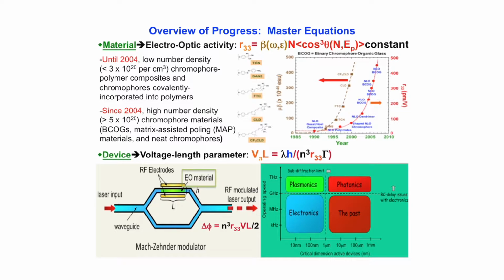Now, if we look at this curve, of course, electro-optic activity should relate to the product of dipole moment times the molecular first hyperpolarizability. If we look at the evolution of experimental molecular hyperpolarizability as a function of preparing different molecules that define the state of the art in various years, we note that we achieved this rather dramatic improvement of mu beta as a function of using better acceptors and longer chromophores. Now, unfortunately, this curve leveled off at this point in time. And if we had truly independent particles, this measured electro-optic activity, r33, should track exactly this curve. But you see it doesn't.